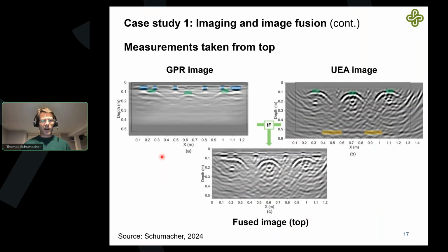These are the measurements from the top. We have the radar showing up some mild reinforcing bars on top. There's no pre-stressing, but some simple mild bars. And we can also see the voids here. Because the layer of steel is not as dense, at the bottom it's about 50 millimeters, the spacing of the strands, and they're 13 millimeter diameter strands, pre-stressing strands. So that's very dense. It's hard for radar waves to penetrate through that layer. Here it's much more open, so we can actually see the voids.